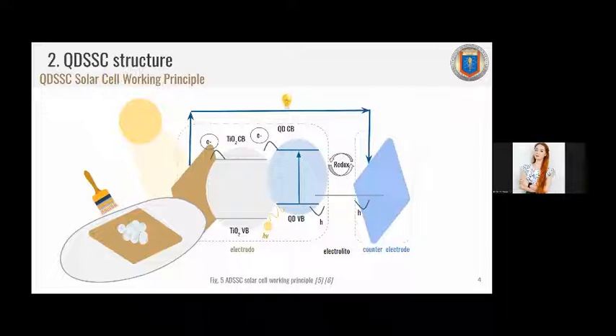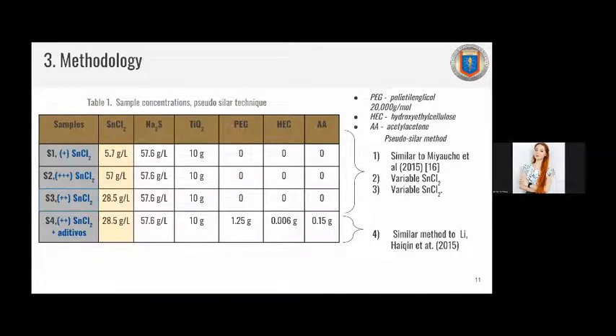As I said, the quantum dot sensitized solar cell material was developed in the form of a paste at room temperature, without the use of heat, using a pseudo-SILAR technique and a very energy efficient method, which is the ultrasonic bath. Here you can see the four main sample concentrations that were made. They used the following reactants: tin chloride, sodium sulfide, and titanium dioxide. These were the three main reactants used to obtain titanium dioxide with tin sulfide decoration. Some additives were used as well, such as polyethylene glycol, hydroxyethyl cellulose, and acetylacetone, because they were thought to increase the stability of the size of the quantum dots.